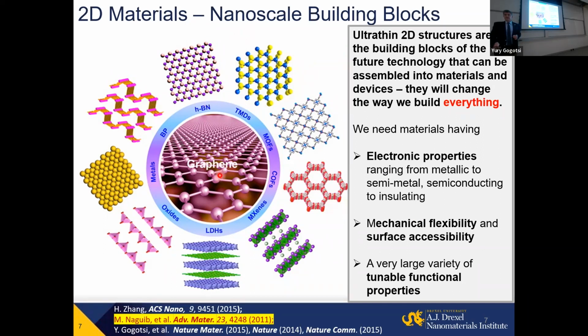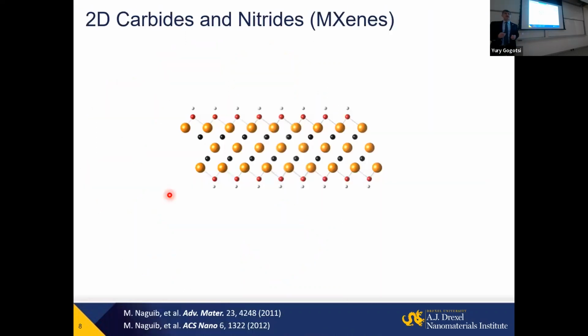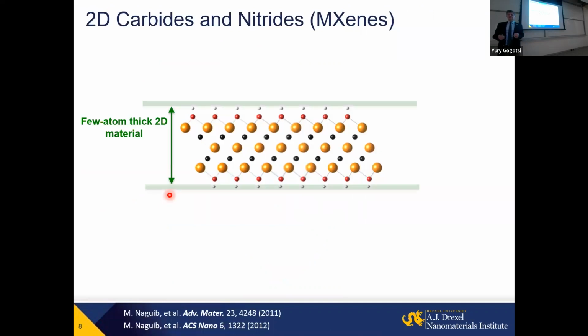But graphene, which is always praised for its high conductivity, in fact, is a zero band gap semiconductor. It doesn't have carriers. You have to dope it or create defects to create carriers in graphene. MXenes that we added are true metals, many of them, the majority of them. So they added two-dimensional metals to the family of 2D materials. And this is why they have this important role.